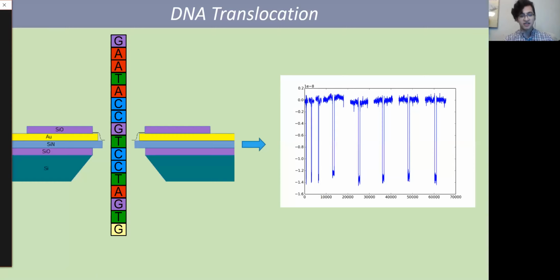As the DNA is getting flushed into the cell, we apply a positive voltage bias. Since the backbone of the DNA is negatively charged, it's going to drive the DNA through the micropore and through the graphene nanogap. As the DNA is getting driven through the nanogap, we measure its ionic current, or more precisely, the blockage of the ionic current. Every time the DNA goes through, we will see a drop in the ionic current. That's why we are able to identify that DNA is going through and we're actually reading translocation.